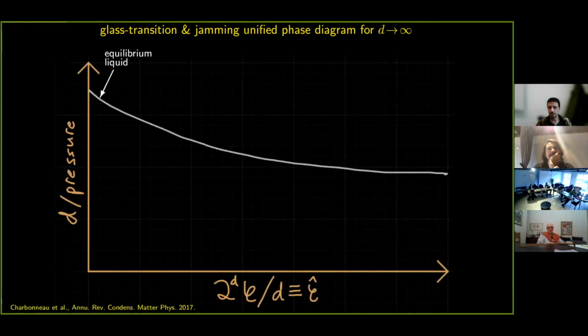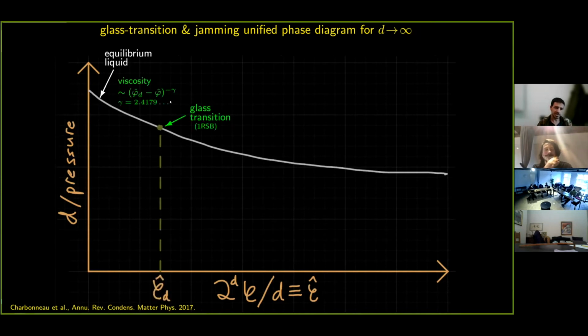I'm going to walk you through it as slowly as I can. On the y-axis, we have the inverse of the pressure. On the x-axis, we have essentially the packing fraction, scaled in a way that has a well-defined limit in the limit of infinite dimensions. So this is the equation of state for the equilibrium liquid. Then as the system is compressed, there's a glass transition that takes place at a packing fraction called phi d. It has been resolved that the viscosity diverges with a true singularity at this packing fraction phi d, and the exponent has also been calculated from the theory,